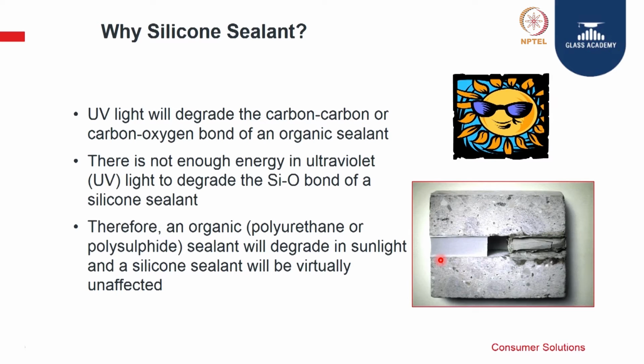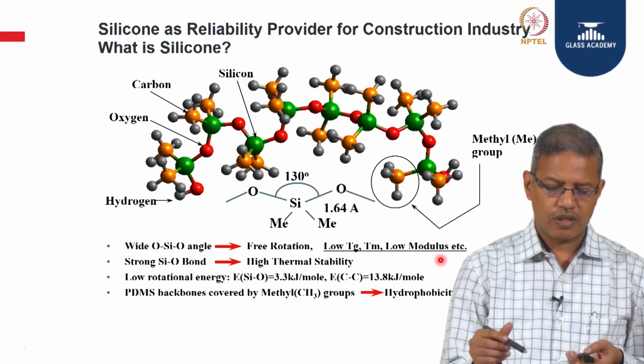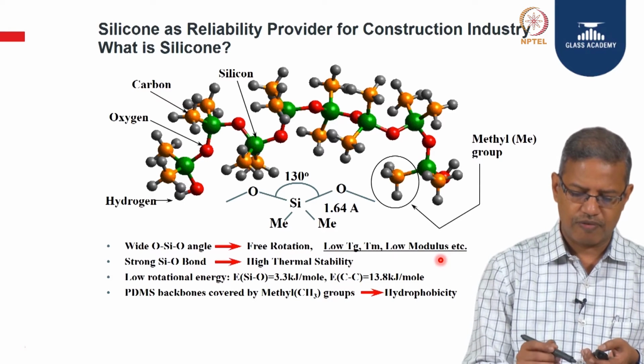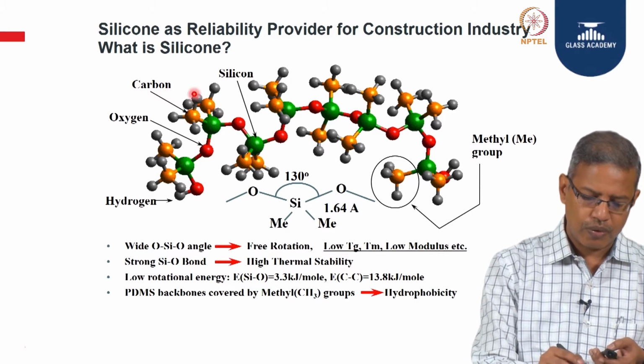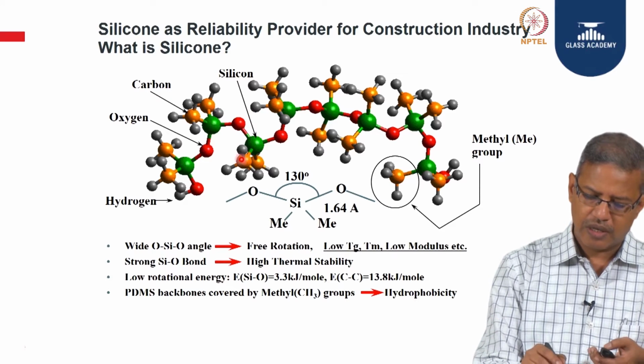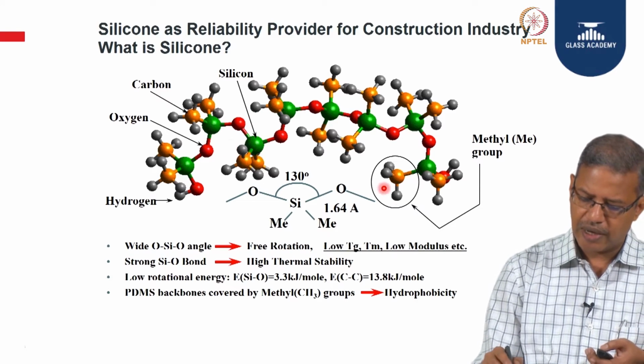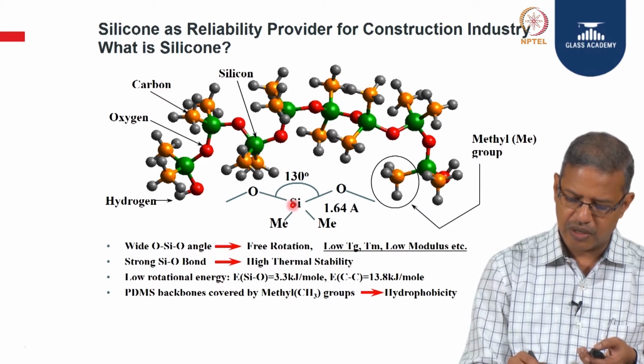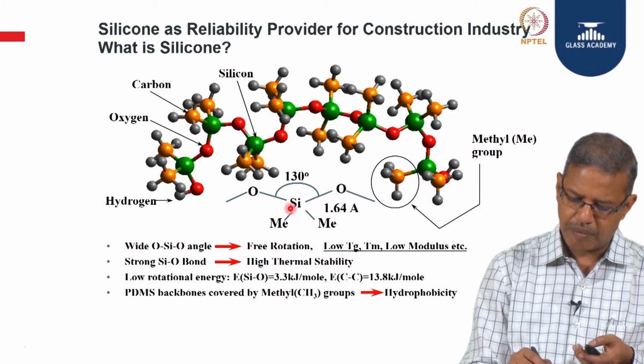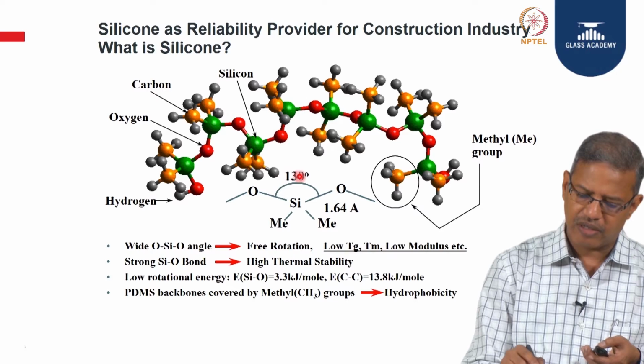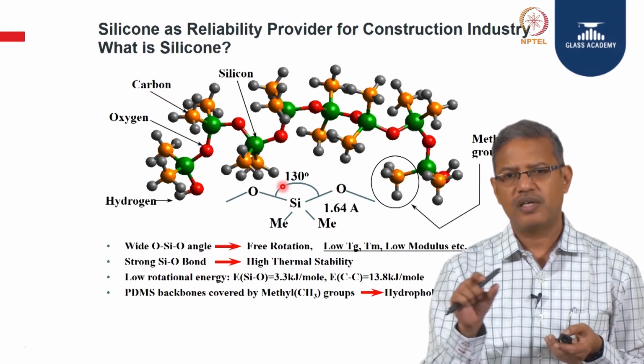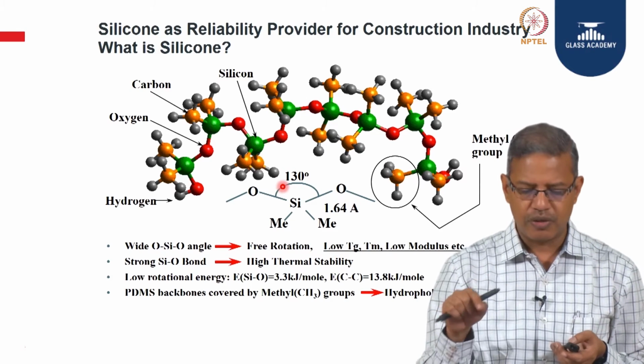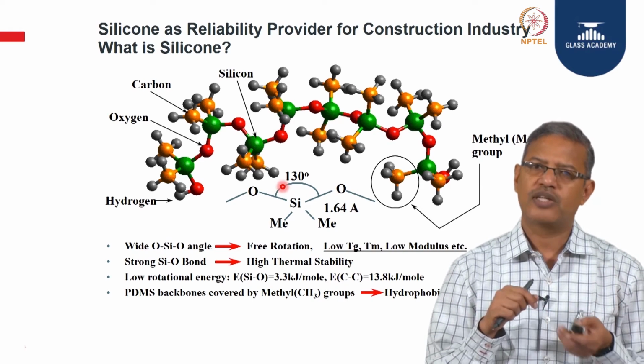So, this essentially proves that the product which has to be used for an application like construction should have very good long term durability. Okay. This is again explaining the structure of the material. You can see the bond angle of silicon. If you look at the silicon oxygen silicon chains, the angle is around 130 degrees. This 130 degrees of angle between two bonds gives it excellent flexibility.